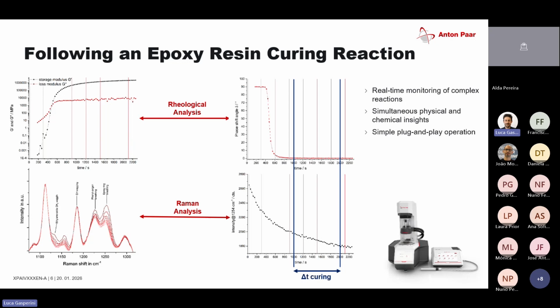And as you can see here, at 1,000 seconds, it's not fully cured yet on a chemical level. On a physical level, it looks like it behaves very elastic. But on a chemical level, it still needs some time to cure. So when you just take a look at the Raman perspective here, you can tell that it's actually fully cured at 2,000 seconds.